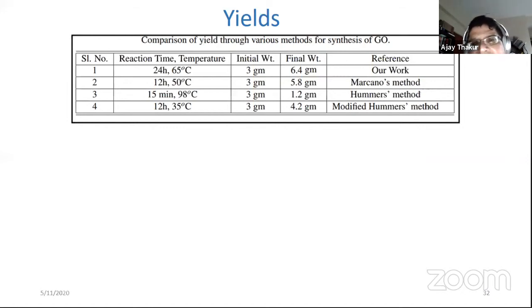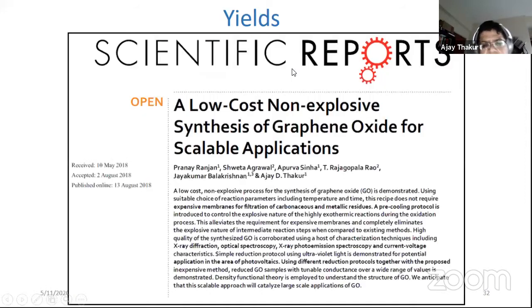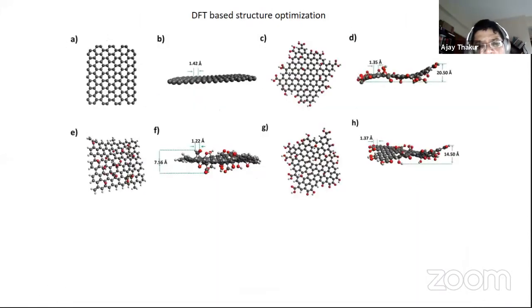And over here, we just summarize the yield for the starting weight of 3 grams of graphite. As can be seen, compared to Hummers' method or the Tour method, which is also called Marcano's method, our method was able to give a much higher yield. And this work was published by Pranay.